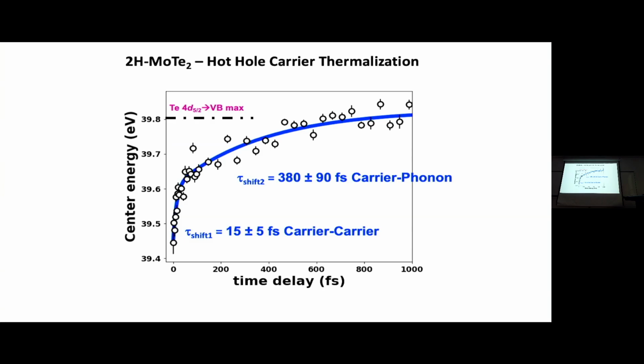So it goes from a non-Fermi-Dirac distribution to a Fermi-Dirac distribution in like 15 femtoseconds in this material. And then we see a slower part, and this is when the hot carriers are interacting with the phonons, and that's the decay of the hot carriers due to interacting with the lattice, the lattice interaction due to the phonons.